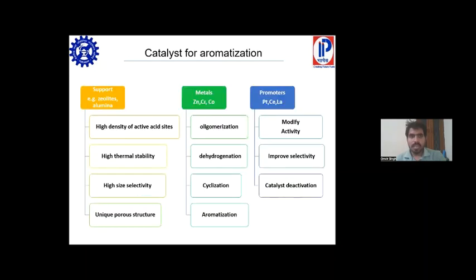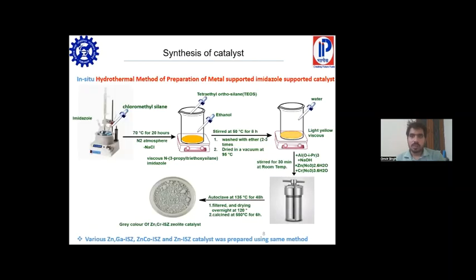For this purpose, I have synthesized different materials. From them, we found that different metals play different roles, and different promoters also enhance the aromatic selectivity and reduce catalyst deactivation. After modification with different promoters, we come to the synthesis part of the catalyst.